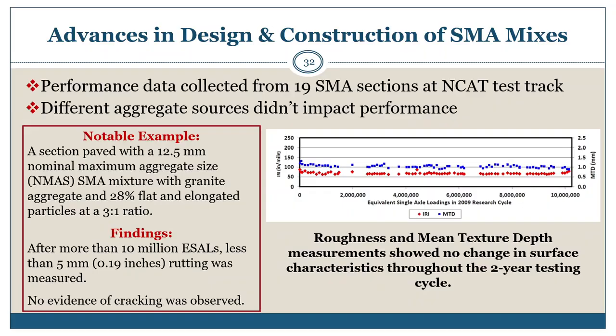A notable example from the NCAT study was a section paved with a 12.5 millimeter nominal maximum aggregate size SMA mixture with granite aggregate and 28% flat and elongated particles at a 3:1 ratio. The findings on that section were that after more than 10 million equivalent single axle loads, less than 5 millimeters or 0.19 inches of rutting was observed, and there was no evidence of cracking on that section.